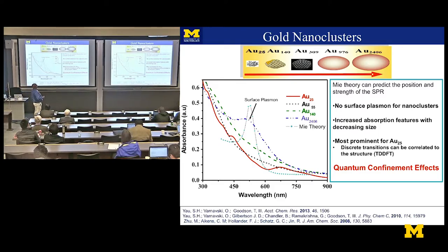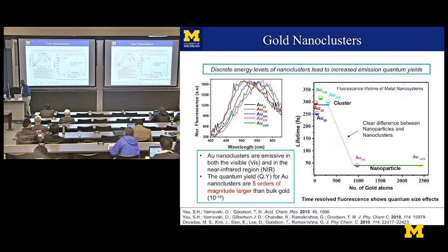You get increased absorption features with a decreasing size. And then the most important thing is that there's these discrete transitions later correlated with time-dependent DFT calculations, suggesting that there was indeed confinement in these tiny clusters. Big deal. It means that clusters actually can behave like molecules, if you will. And you could look at the fluorescence.